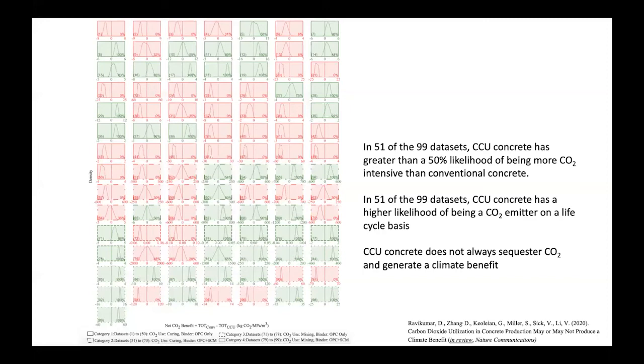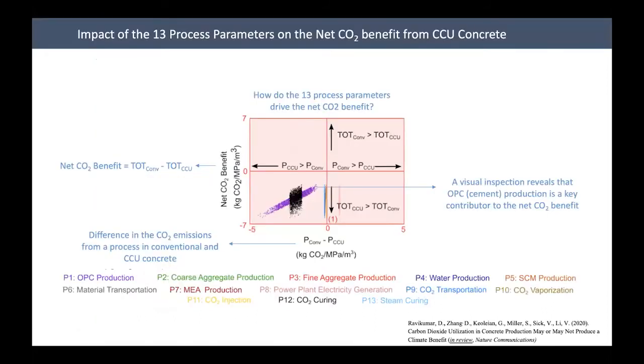Note that CCU concrete does not always sequester CO2 from a life cycle perspective. It's almost a 50-50 probability that it increases the climate burdens when compared to conventional concrete. So, as I told you, there were 13 process parameters that we considered in this model. We wanted to understand visually what is driving the net CO2 benefit. What's the most important process parameter driving the difference between CO2 emissions from conventional and CCU concrete.